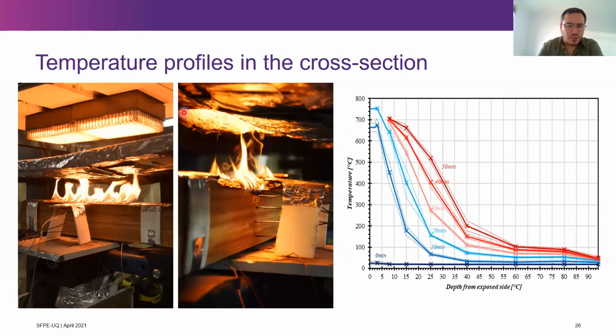In order to measure the temperature profiles and the in-depth temperatures in our specimens, we performed some control tests with in-depth thermocouples. We didn't want to affect our specimens during the fire structural experiments. So we performed some tests with the same conditions that we had in our structural test, to measure the temperature distribution in the beam.